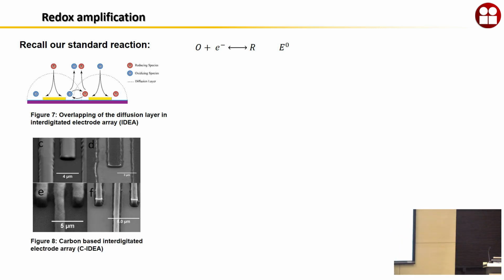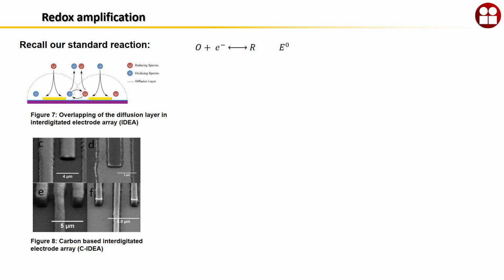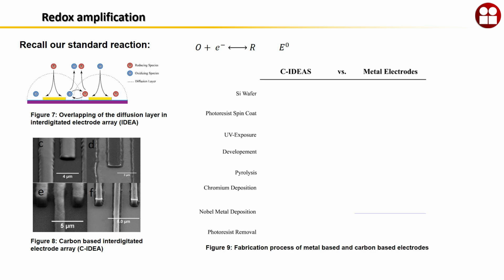So as you can see, these electrodes are probably 1 micron height, made from carbon, extremely stable at the pH of interest for biological detection, which is about 7. And it also has a high aspect ratio. It means that instead of having one of these and getting only 1 or 2 electrons out of the system, you can get multiple of these electrons out of the system.